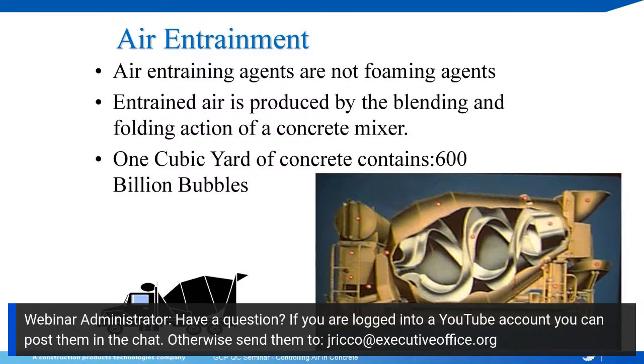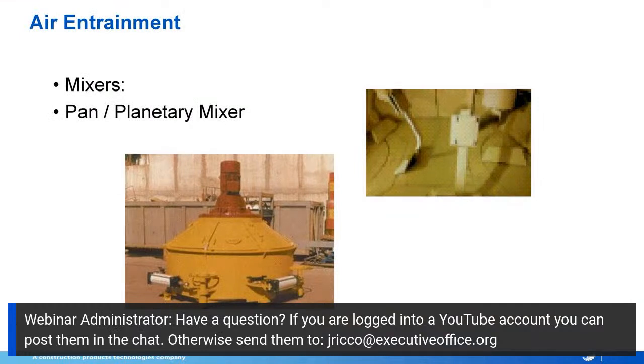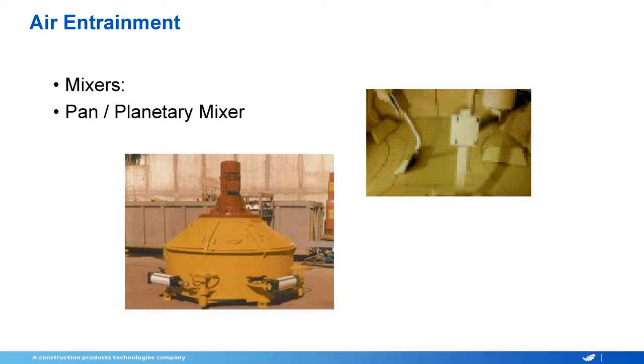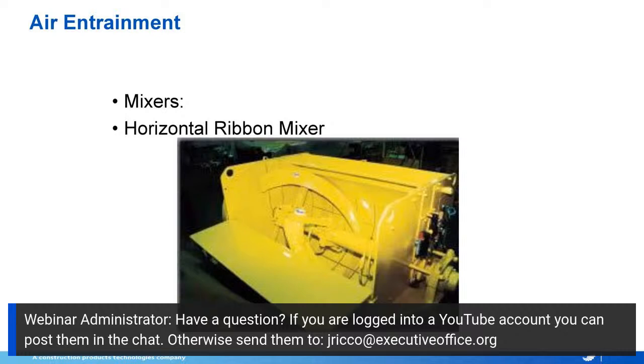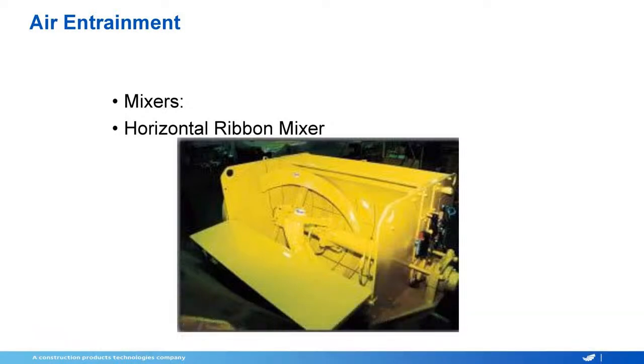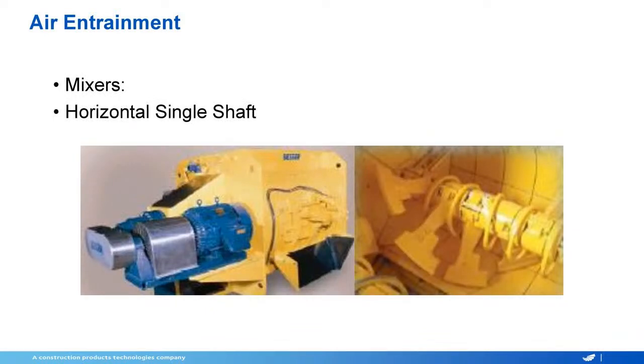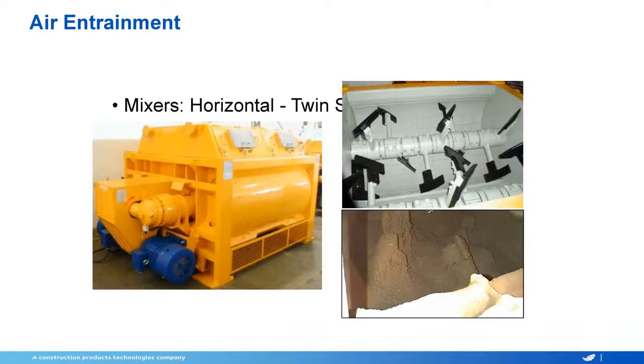So there are a number of different mixers that we can use. Some of you guys use the drum mixers, which are stationary. Some use ready mix trucks to move the concrete out to the forms. We have planetary mixers, pan mixers, and ribbon mixers. I don't see as much of these anymore as I used to. We have the single shaft and the twin shaft mixers. All of these will take the same materials, same amounts of material, same amount of air entraining agent, and give you different air contents. That's just because the mixing action is different.